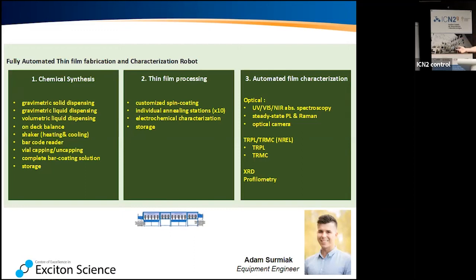And then you can start scratching your head about what materials to choose to contact it and to make a good solar cell. And then also XRD, so we can get an XRD and a profilometry. The idea is that everything moves on in 5-minute clock speed. So every 5 minutes you get a new device made and fully characterized. And the idea is also that we can press the button and have it run for 24 hours, hands off.